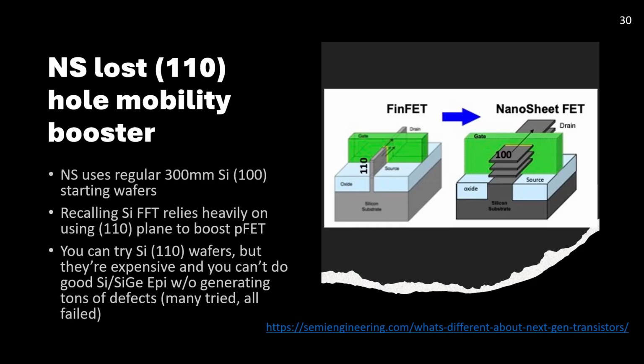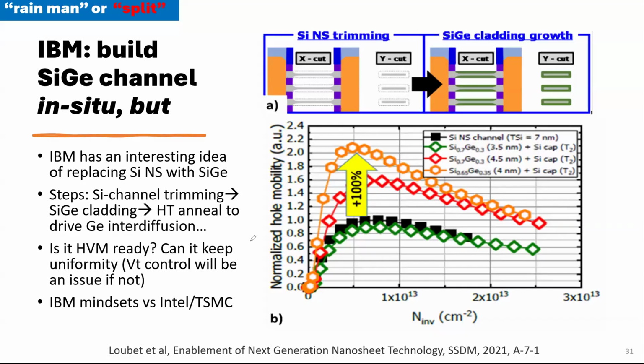But if you can't change the starting wafer, what about this? IBM in 2020, 2021, proposed this. How about doing it in situ? I call it SiGe cladding growth. So I have a silicon here, and you trim it down a little bit. This is about 5 nanometer, and you trim it like 2, 3 nanometer. Okay, so you see here, 3.5.